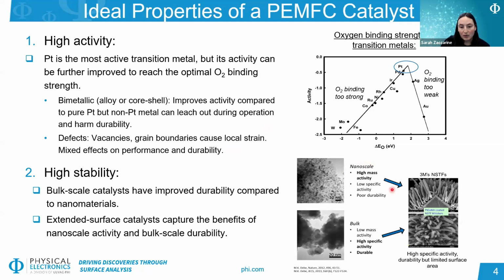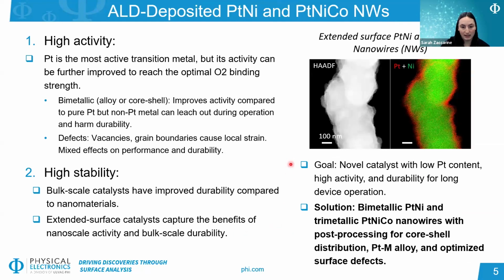So nanoscale catalysts such as nanoparticles are generally known for having very high activity. However, they can have some durability concerns like agglomeration or Ostwald ripening and a variety of other different mechanisms. Bulk materials are generally considered slightly more stable over the long term, but they can have a lower surface area and other trade-offs. So a new area of catalyst was introduced called the nanostructured thin film, which is essentially an extended surface catalyst where you can have high specific activity, high surface areas across a substrate, but still have slightly better durability of more bulk scale type materials. And in this work specifically, we're using this concept to create extended surface nanowire structures.